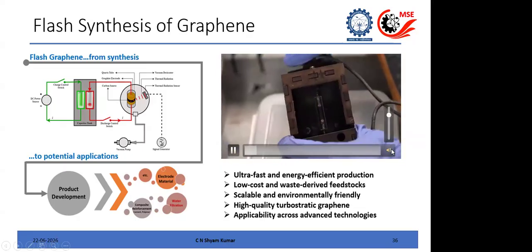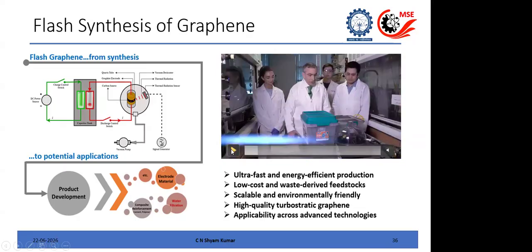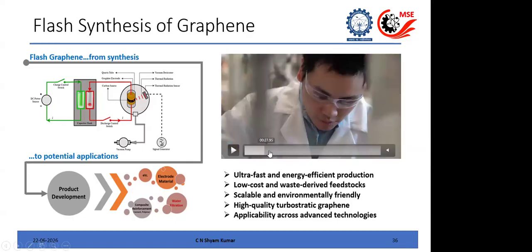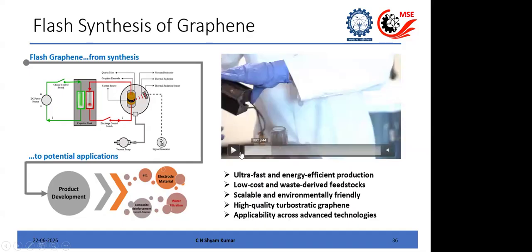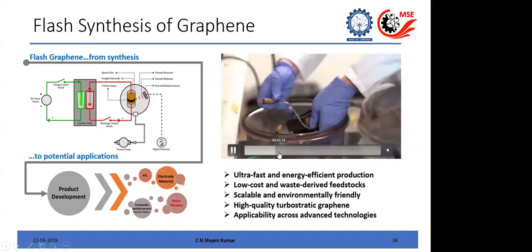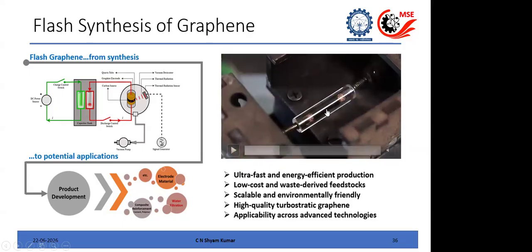So what they do is that they take initially pyrolyzed conducting carbon from any biomass or anything, or mix it with some conducting fillers, and they give very high voltage and very high current for a very short time. So, like in the case of laser, you have a very fast conversion of these organic things to highly graphitic carbon. I think there is a small video where you can see. So this is the carbon inside.